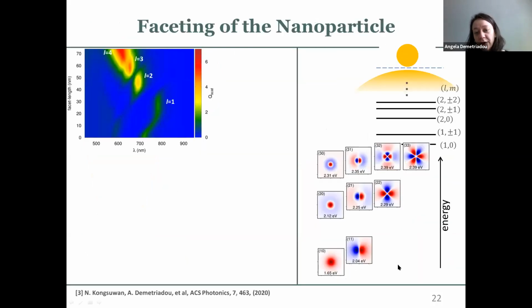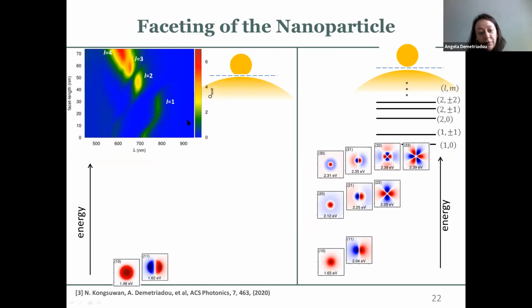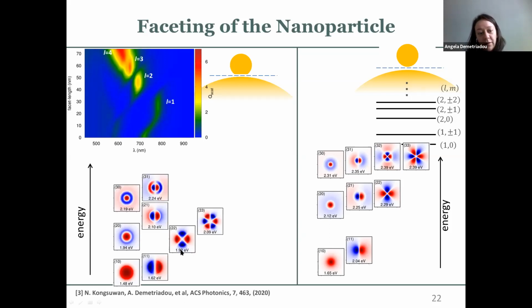And what we realized after analyzing the higher order modes in the system is that as you create a facet on the small nanoparticle here, you're shifting your modes energetically. The first two modes, for this particular facet size that I picked here, which I think is 20 nanometers, move energetically a little bit lower, but they keep their order. However, for the second order mode, you see this mode here, which used to be up there, being lower energetically. And for the third mode, you see something like that, fourth and fifth, and so on. All these higher order modes are very, very dark. So they start interfering with the emission of these modes, which are my bright modes. And that's why you see this behavior when you change the facet size. So you end up mixing the frequency where these modes are up here.